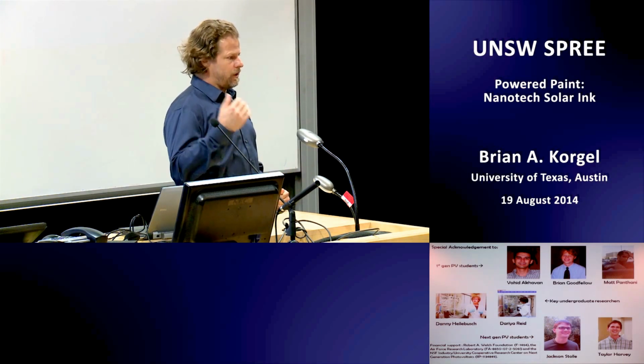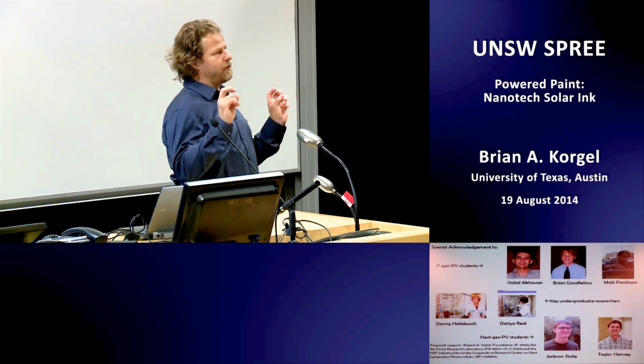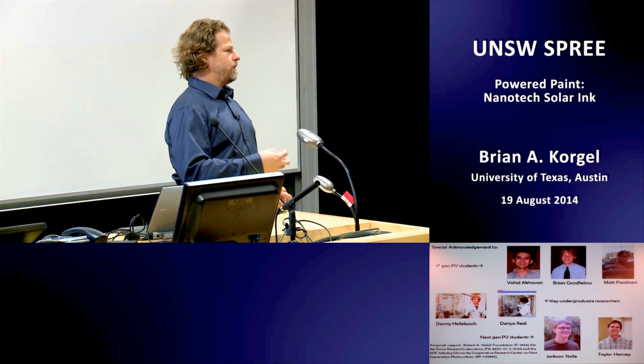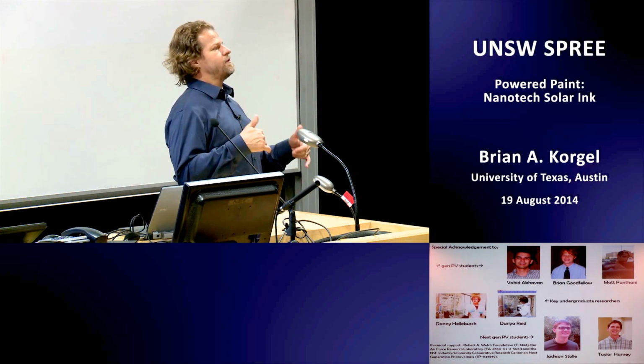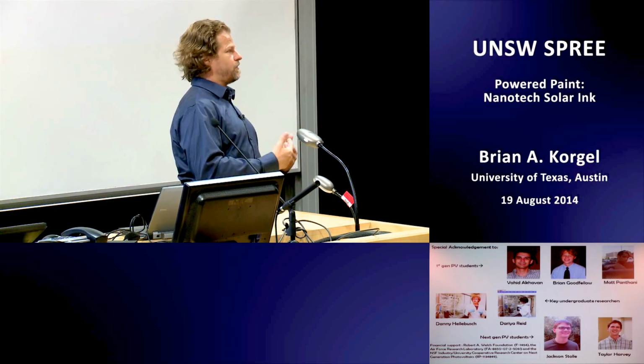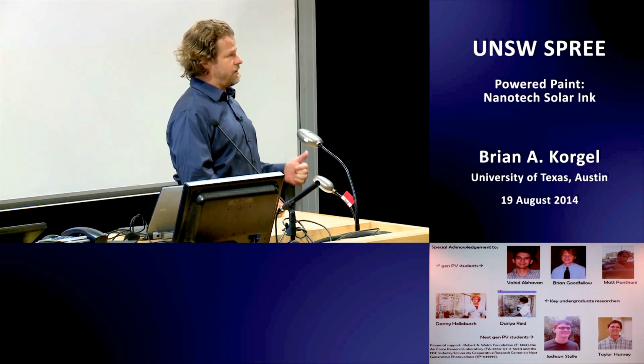So what they'll do is deposit the nanocrystals with good capping ligands that enable good dispersibility. And then they'll strip those ligands out with a solution process and do things like exchange with halides, things that are not good capping ligands, but that will passivate the surface electrically. So that's been the approach in lead sulfide.